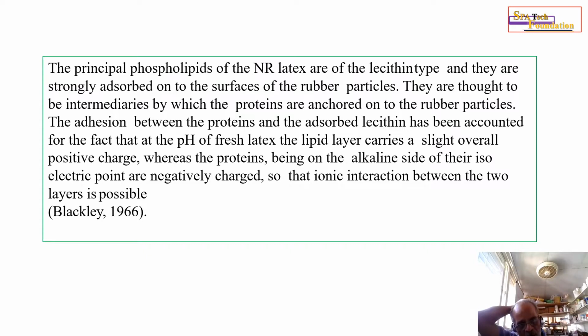The principal phospholipids of natural rubber latex are of the lecithin type, and they are strongly absorbed on the surface of the rubber particle. They are thought to be intermediaries by which the proteins are anchored onto the rubber particle. The interaction between the proteins and the absorbed lecithin has been accounted for by the fact that at the pH of fresh latex, the lipid layer carries a slight overall positive charge, whereas the proteins, being on the alkaline side of their isoelectric point, are negatively charged, so that ionic interaction between the two layers is possible.